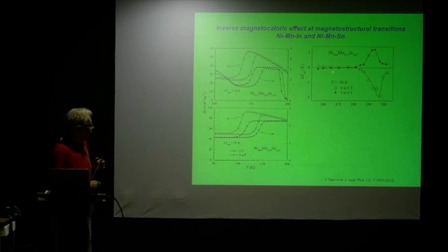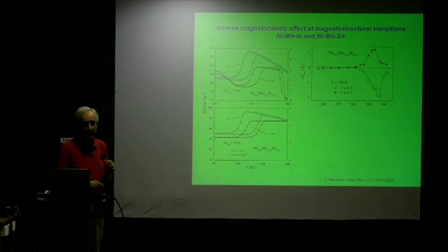So what you do is, let's take this point for example, you apply a magnetic field, you get cooling, which is about -1 Kelvin, and then after you've waited for some time, you go from 5 to 0, and you see that you don't get the 1 Kelvin back, it gets stuck at about 0.8 Kelvin, let's say. So you're not getting back what you put in.